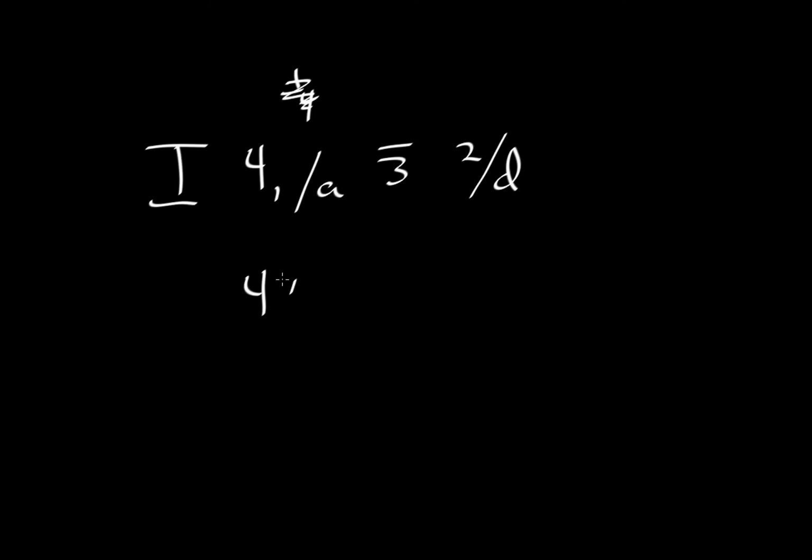Get rid of that translation distance, and we just have a regular 4. That would be perpendicular here to an A glide, but that would devolve into a mirror. Here's a bar 3, nothing special going on there. D for a diamond glide, so that diamond glide becomes a mirror plane, and so this becomes an example of the point group 4 over M, bar 3, 2 over M.